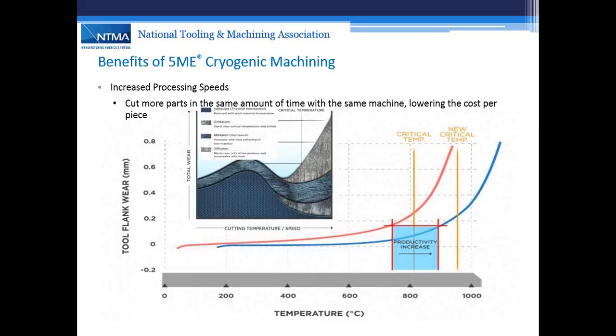Okay. Now, if you look at the embedded graph, that looks at tool wear, and it looks at abrasion, adhesion, oxidization, and diffusion. Oxidization and diffusion are heat-activated wear mechanisms. They kick in once you get to the critical temperature. So again, if we move that critical temperature to the right 20–30%, then those two wear mechanisms do not kick in, and therefore you extend your tool life, or are able to machine faster before those tool wear mechanisms kick in. Okay, next slide.